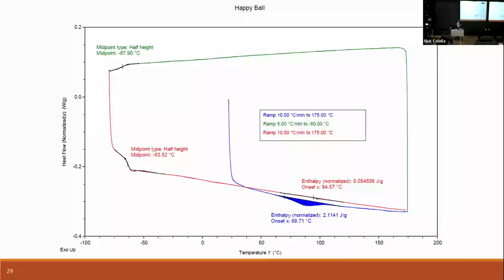That's going to have some thermal history. The first heating cycle is going to reveal that thermal history, and then we're going to heat to erase it, then cool it down and heat it again. And we've effectively erased the thermal history. So now the second curve is just characteristic of that polymer. It's not about how you processed it. It's just for the material itself.